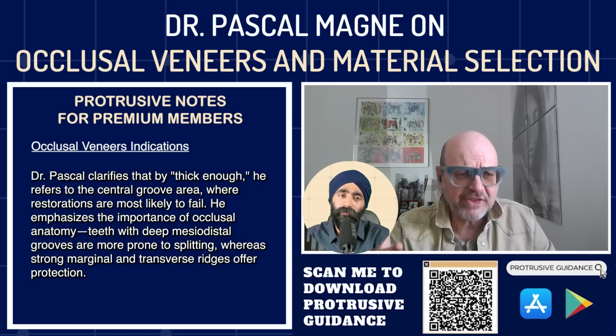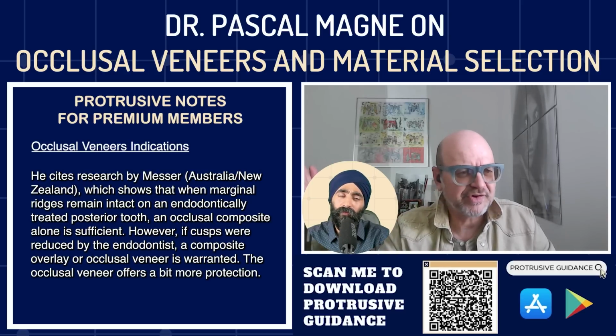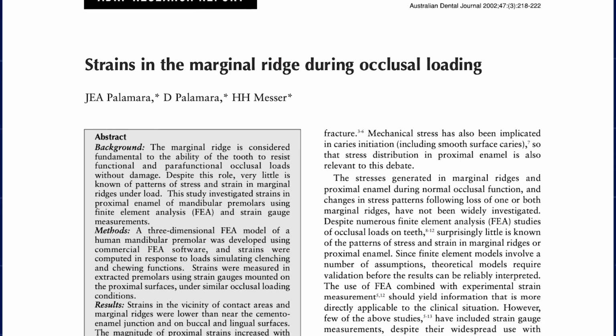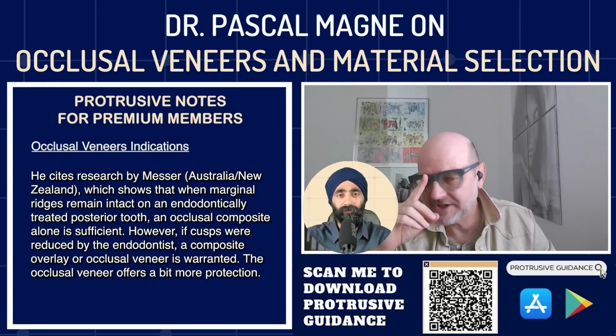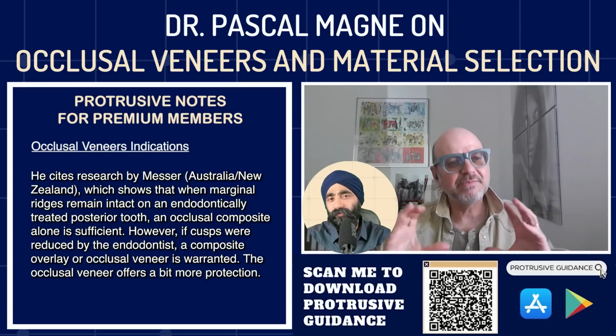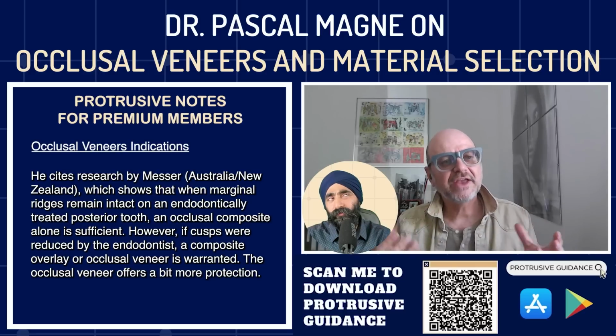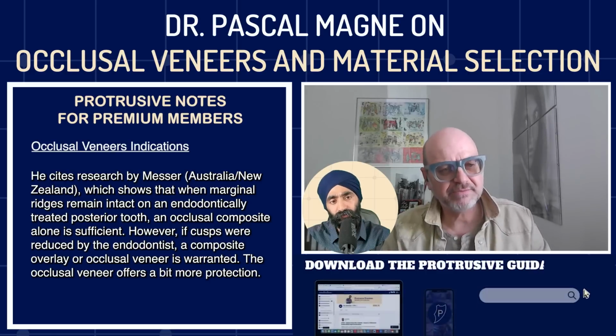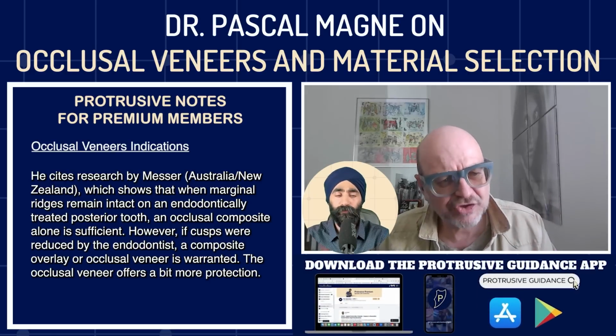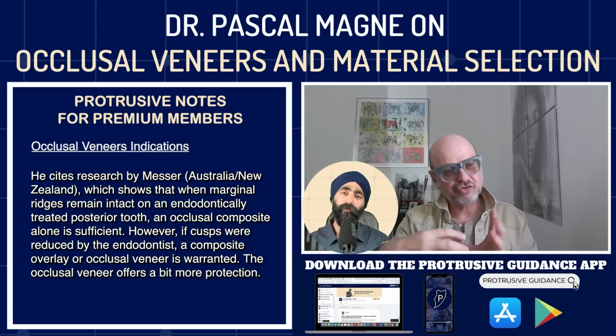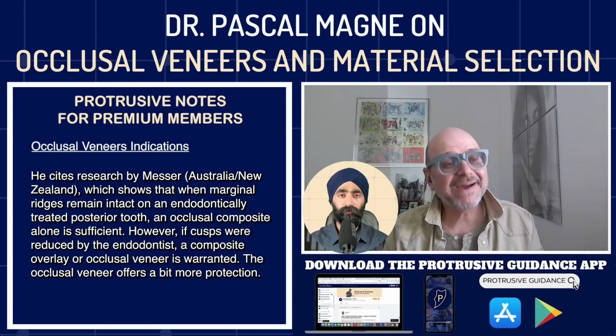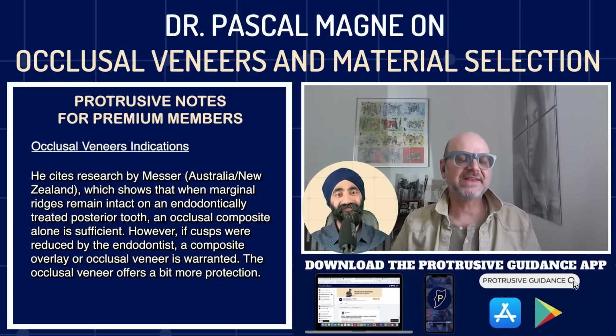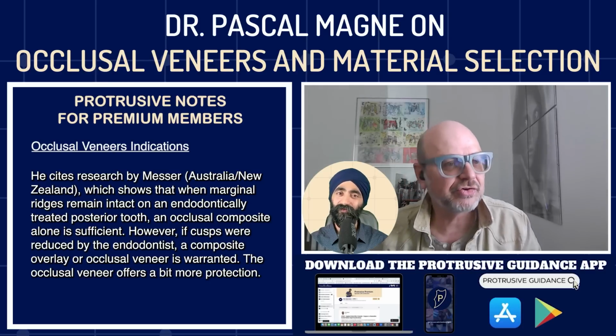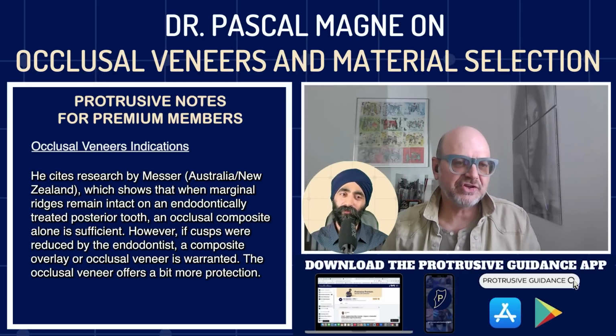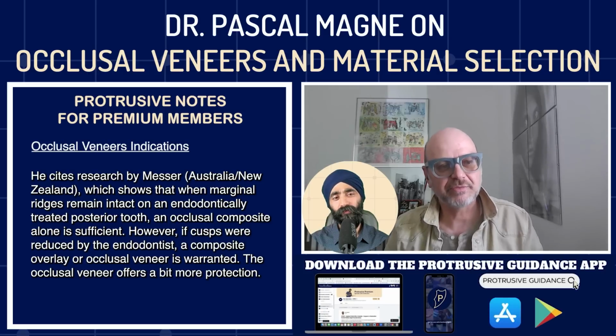And so that's why we know that, and there's a lot of study by a fellow from Australia or New Zealand, they called Messer. And they were actually also in Minnesota when I was doing my PhD there. And they show that if you have intact marginal ridges on a posterior tooth, and you have an endo preparation and endo treatment, but the marginal ridges are intact, you need nothing else than an occlusal composite because of the remaining structure protecting the tooth. But it might be that the endodontist has reduced those cusps, and in that case, you could extend the composite, or you could do an occlusal veneer.